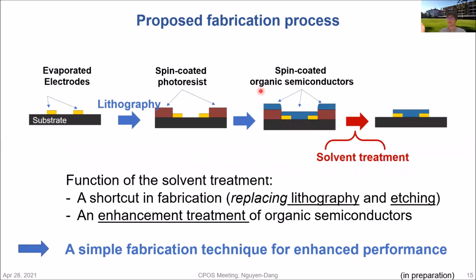So that's what I mean. I proposed a new fabrication technique. On a substrate with the source and drain already evaporated, we just keep an opening on the channel side, and then we spin coat the organic semiconductor. At this point, instead of having another lithography process to define the channel and another etching process to bombard the material and remove the extra organic semiconductor, and then another step of stripping, we just require a solvent treatment. This solvent treatment step would replace at least two other steps in the fabrication techniques that are currently available.